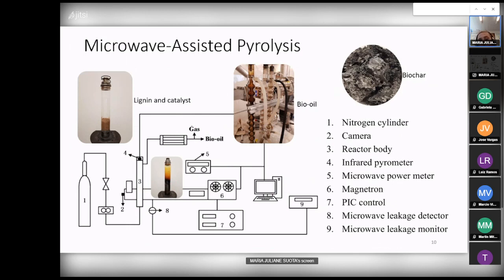At that moment, I hadn't collected the gas for analysis, but pyrolysis is a very promising reaction where we can obtain solids, liquids, and gas from biomass, and use them further in several applications. So here in this tube, this reactor, we can see the lignin mixed with the catalyst in a uniform way. We can't separate both. And this material was placed in this area and irradiated with microwave energy. After 20, around 25 minutes, we collect all these materials for analysis.